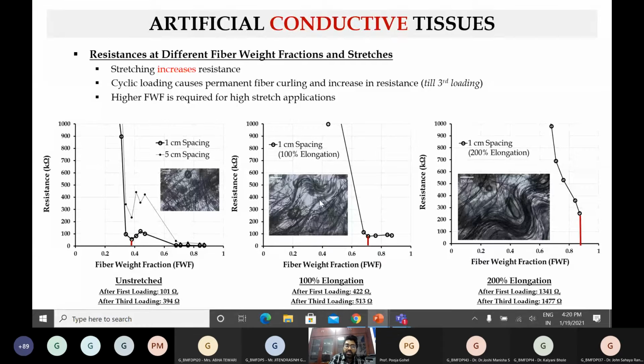That is how much we need to be able to have the same below 1000 ohms resistance for this one as well, a very similar current path as before. We need so much fiber weight fraction for this elongation. For a 200% elongation, even more. If we look at the undulations here, this is going through even higher undulations.